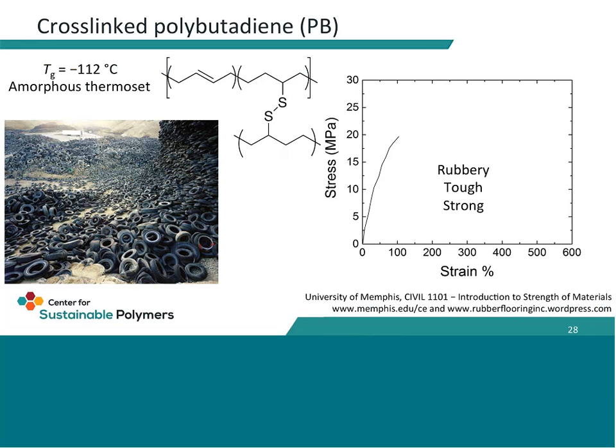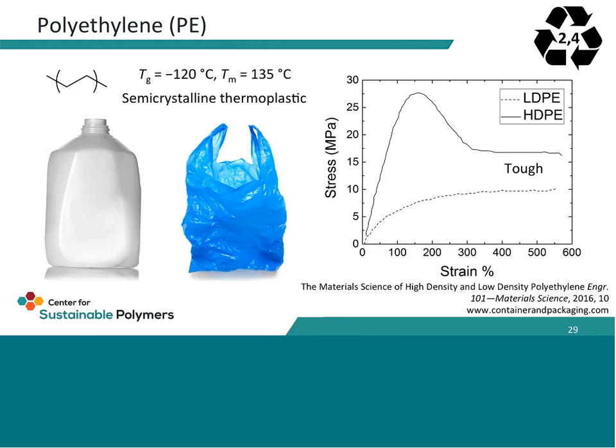We don't need to introduce chemical crosslinks in order to get this kind of solid material, and so like Annabelle was talking about in the question and answer section, polyethylene does exhibit solid-like behavior. It has very low Tg, below minus 100 degrees C, but it also has a very high melting temperature. So at room temperature, it will be rubbery because it's above its glass transition temperature, but these physical crosslinks of the semi-crystalline domains keep the polymer from flowing like the silly putty would do, and instead